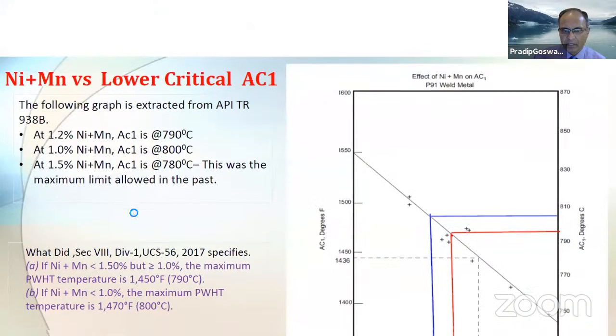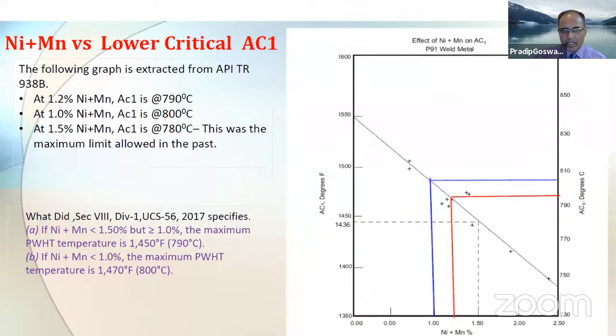This is taken out of API 938B. I've tried to plot these lines with respect to the various nickel plus manganese content. As you see here, when it is 1% nickel, the AC1 temperature is close to 800 degrees or a little above 800 degrees centigrade. When it is 1.2%, the AC1 temperature is approximately 790 or so. As per the earlier rule, that is 1.5% nickel plus manganese maximum, this AC1 temperature was of the order of 780 degrees centigrade.